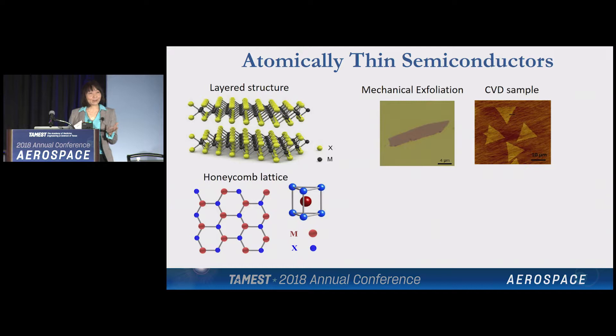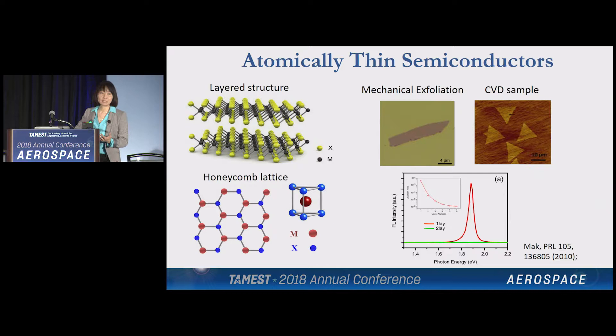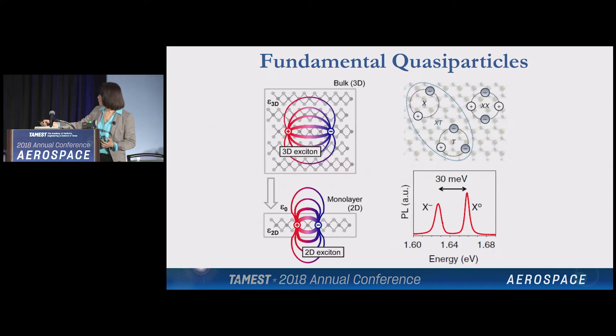We do this low-tech scotch tape method, and I have an army of undergraduate researchers that have mastered the skill of creating these materials. Smarter material scientists, like Delia, would use a more sophisticated tool like chemical vapor deposition. Here's one of the early works showing that even when you just peel off one layer — the green light represents emission from two layers of material — when you peel them to a single layer, they suddenly become very bright light emitters. Again, this is because we actually change the band structure and where the electrons are allowed to occupy, which dramatically changes their optical properties.